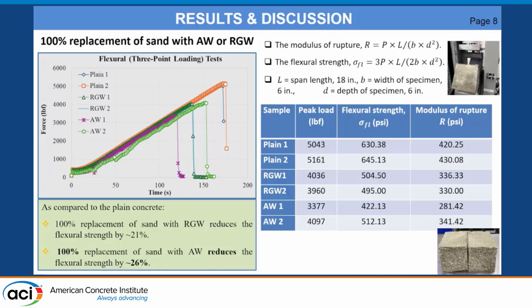So you may be asking, well, the standard says to do three samples. Why are there only two? And it's kind of a bit concerning because there's such a jump in the alumina waste. Well, we only had so much alumina sample and glass sample. We could only run two tests and make the best average out of it.